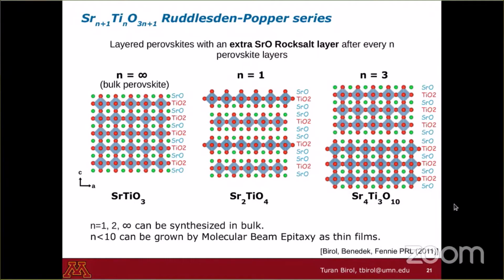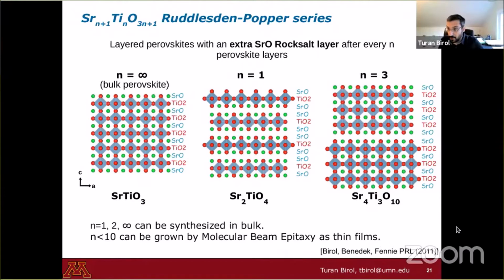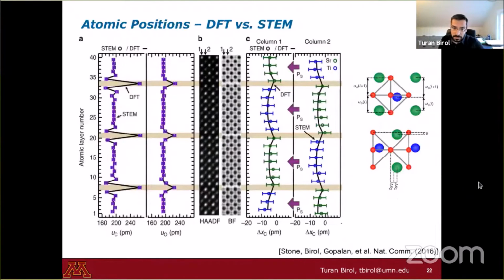Now, we got into this problem right around the time that experimentalists figured out how to grow these types of structures for essentially any value of n that's not too large. And people were interested in whether these materials will become ferroelectric or not, what happens when you grow them on different substrates and so on. So without getting into the details, I just want to show you a comparison of the experimental results with the DFT results. So what we did on the theory part was to optimize the crystal structure by calculating the forces that are applied by the electrons on the atoms. You can find the point which gives rise to the zero force, so the minimum energy. And the output is just the positions of the atoms, which is something you can also check with the experiment.